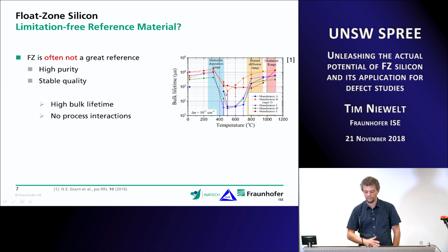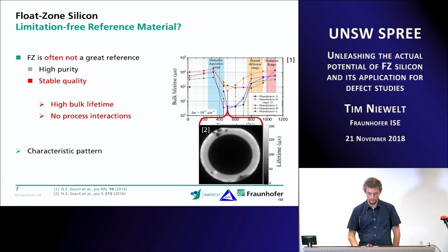And this temperature range that we're talking about is actually touching the range in which quite a lot of our research is being done. So for example, dielectric deposition of surface passivation layers or anti-reflective coatings is actually in this temperature range. And then there is this high temperature range where also the lifetime is affected by the treatments. So yes, the stable quality is kind of an issue.